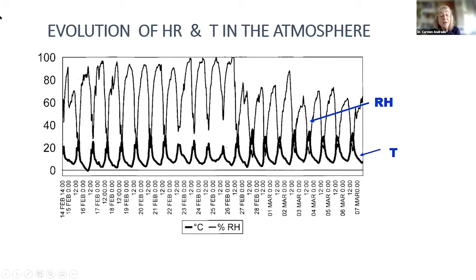And the interpretation, well, I have shown that, and it's known that the daily relative humidity follows a mirror performance with respect to the temperature. That is because relative humidity is relative to the total amount of humidity. I mean, the key parameter is the amount of vapor in a cubic meter of air. The relative humidity depends on how filled with vapor that cubic meter is, and that depends on temperature. In that case, when we lower the temperature, we have a higher relative humidity and the opposite. But this is the daily cycle of relative humidity.